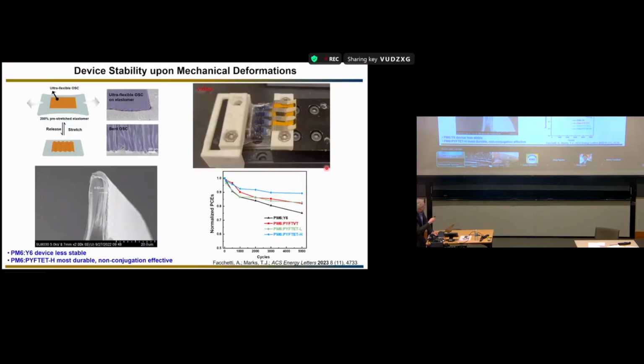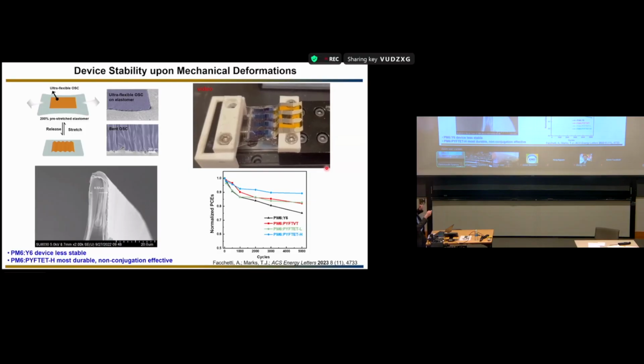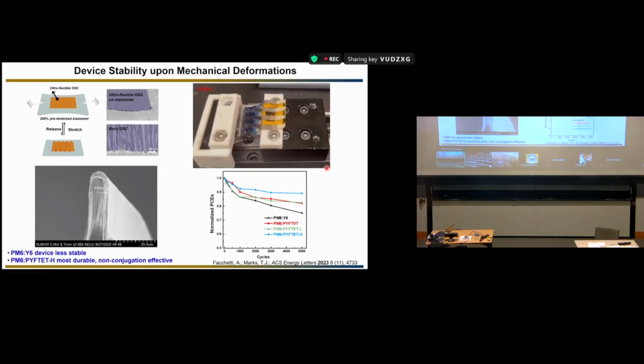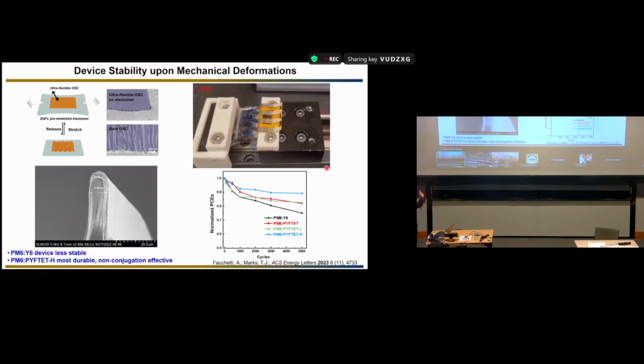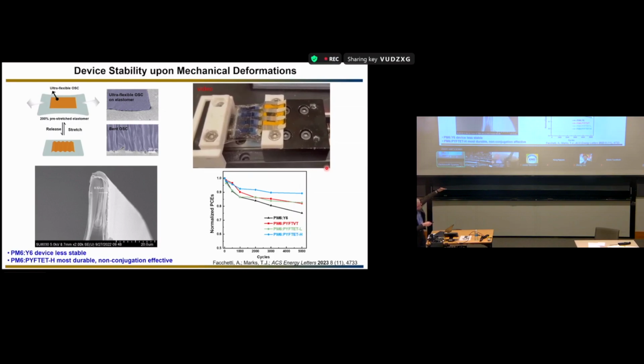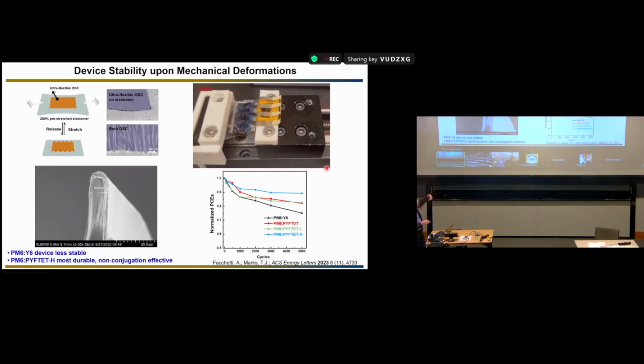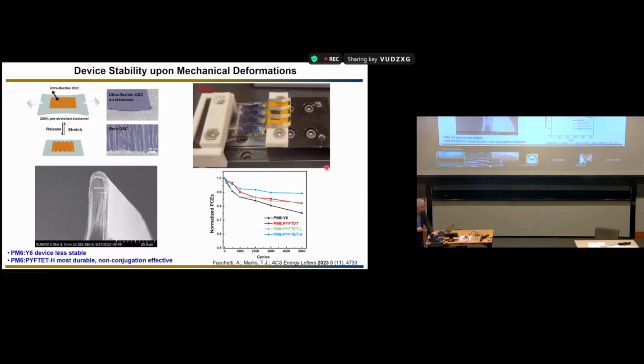And then we can make, based on that, I don't know if the video is going to work, we can start making cells where you start stretching and releasing the strain, and they are much more stable compared to the control. There is a little trick here because you start from a pre-strained substrate, so you're not applying a huge strain. The actual strain that is applied here is in the order of 9%. But there's considerable difference between what we call the acceptor number 2 with the single bond compared to the one with the double bond and compared to the molecular system. So we can start embedding ductility.